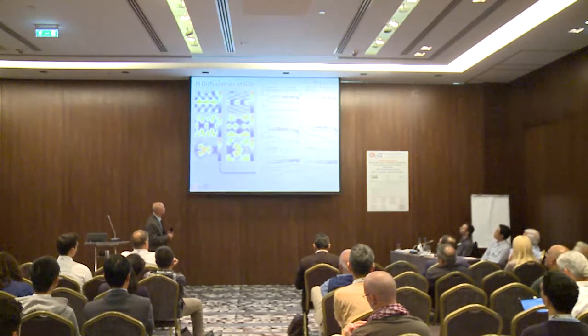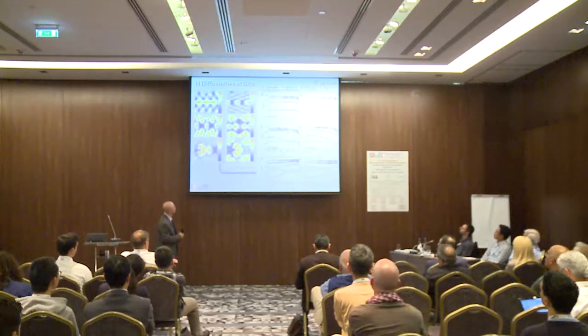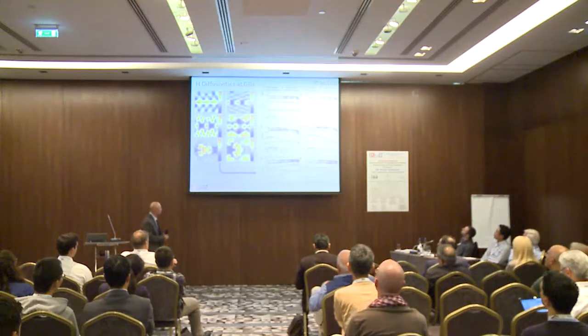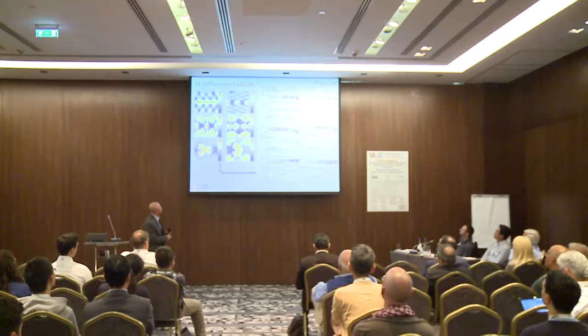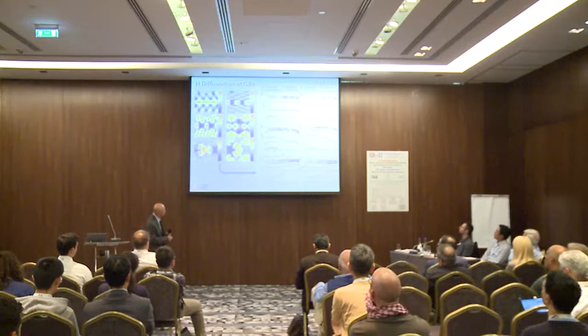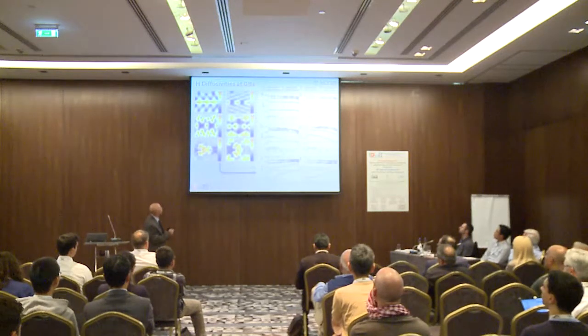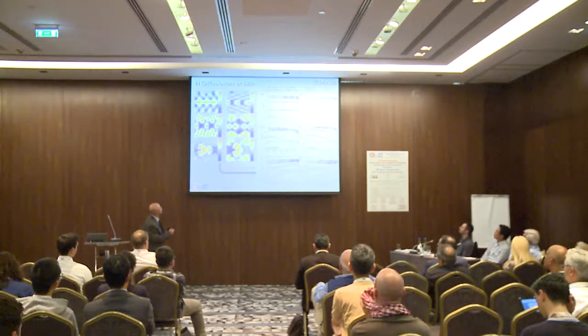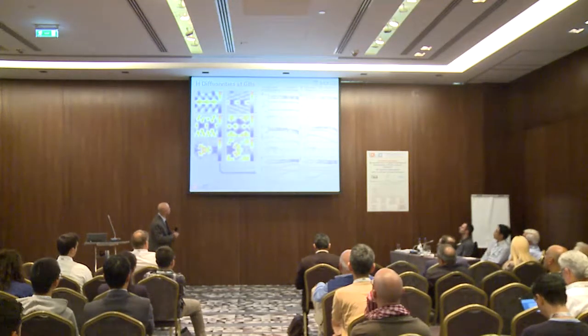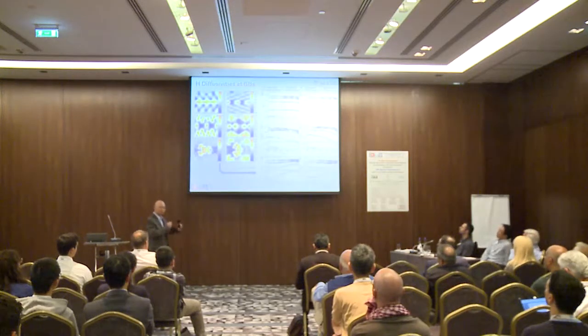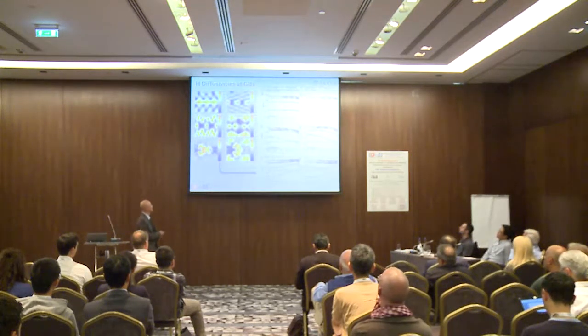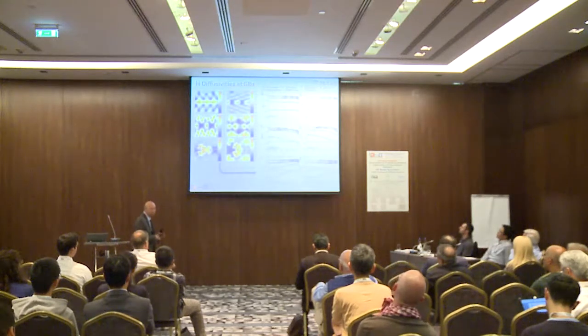Well, for the second one, you have much faster diffusion, so the diffusivity is an order of magnitude larger. Well, for the third category, the diffusivity is much lower. So you see the line I'm pointing to is actually the black line. The black line corresponds to 300 Kelvin. I've also included the data for other temperatures, but let's focus on 300 Kelvin just to have a systematic comparison. You see that we do have three scenarios: bulk-like, fast diffusion, and slow diffusion.